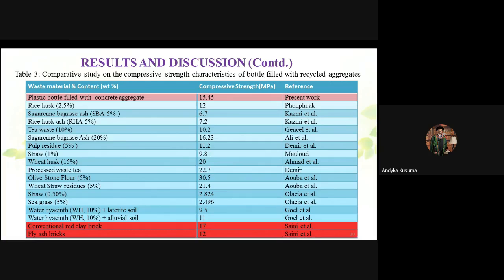After carrying out the literature review, we came to know that the bricks made from agroaquatic waste fibers show compressive strength lower than that of the bricks made using waste plastic bottles and recycled aggregates. Agroaquatic wastes such as 20% sugarcane bagasse ash, 15% wheat husk, processed waste tea, olive flour, and wheat straw residues show much better compressive strength than the developed specimen. It is due to the hollow nature of the fiber materials.